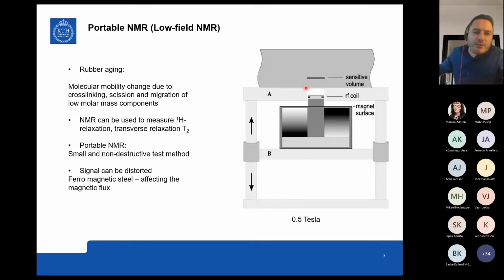So essentially what we do in NMR is that we use this manipulation of the magnetic field to create something that we call a sensitive volume. So it's a 120 micrometers surface area. So it's a very small, thin area, which is 5 millimeters above the magnet. So we create that volume of measurement. And with the help of this elevator device, we can essentially travel up and down and then screen through the sample.